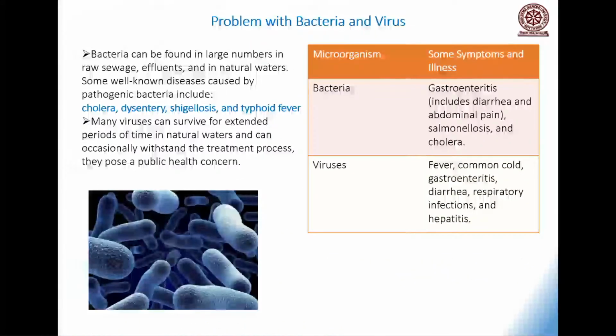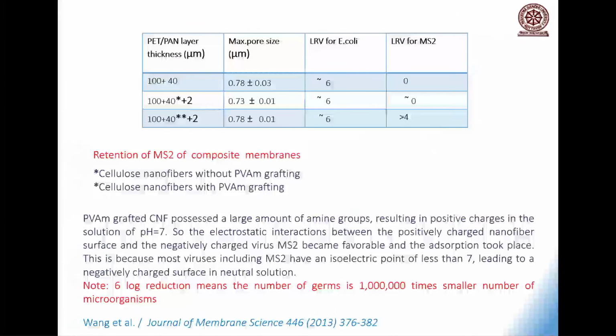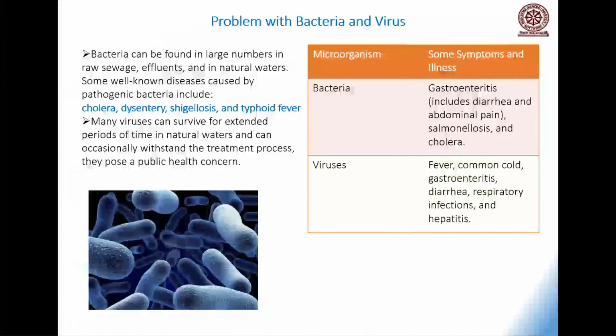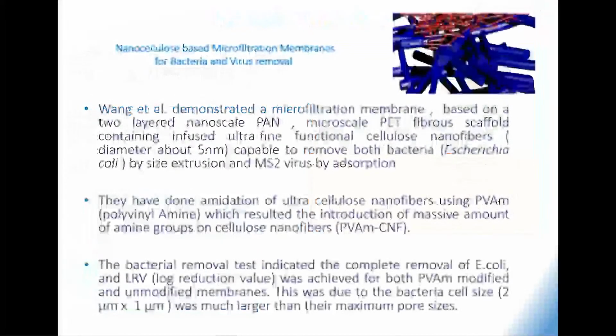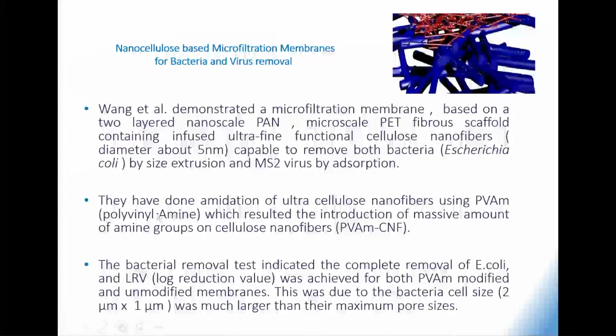Dear friends, we can remove bacteria and viruses. Bacteria and viruses could be removed using nanocellulose. If you want to remove viruses, you have to do some chemistry, because viruses are smaller in size, less than 100 nanometer. So you have to treat nanocellulose with polyvinylamine. See, this is polyvinylamine. If you react with polyvinylamine, you introduce massive amino groups on the surface of nanocellulose. Probably you all know that viruses have a protein envelope that has a negative charge. So once you introduce amino groups on the surface of nanocellulose, there could be electrostatic interaction between the amino group and the virus. And that could be a good way of removing viruses.